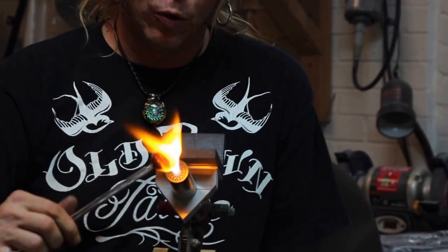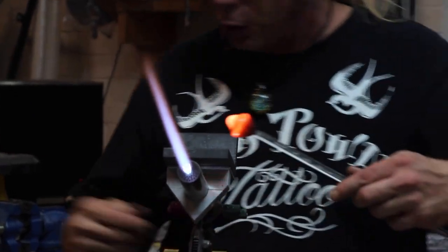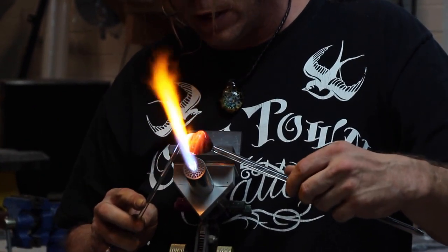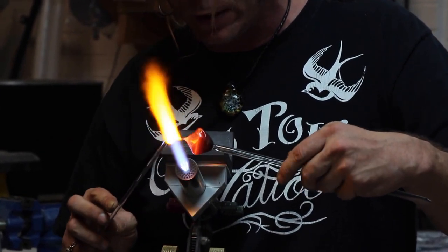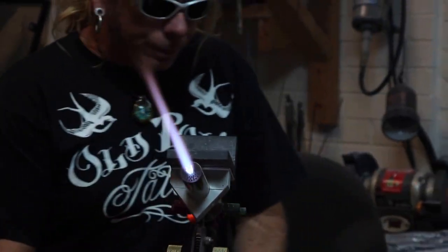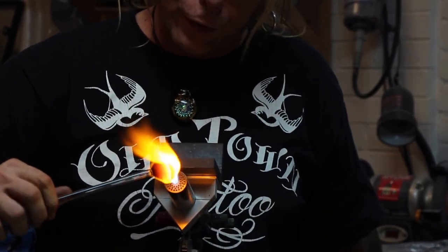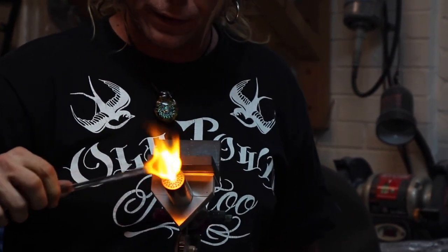The cooler the flame you work during all of this, the better off. Sometimes it slows the process down just a moment, but keeping that nitrogen from coming up is key. And the more and longer you heat these, the more chance of that happening there is, especially if you were unable to get it down to just very fine dust. There's bone fragments in there, the more they get heated, the more they off-gas.